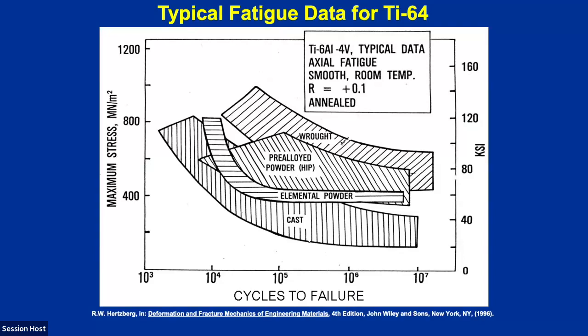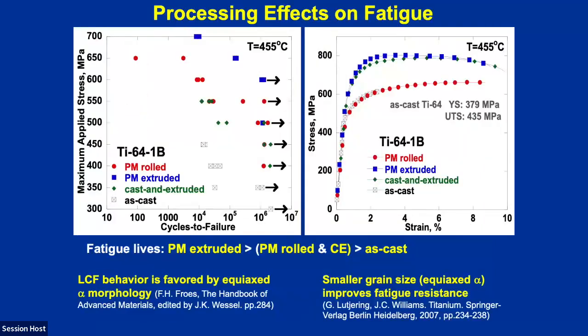By adding in boron. On the left-hand side, we have fatigue tests in tension again, just like the tension tests, at 455 degrees C, and we're looking at cycles to failure versus maximum applied stress. And there are some interesting features. First of all, the as cast had the lowest fatigue threshold stress, and the highest one was the powder metallurgy extruded, which was the same as the cast and extruded 6,4 1 boron.